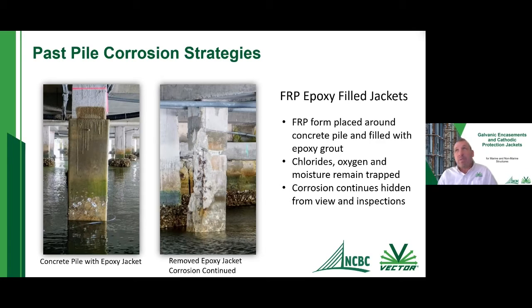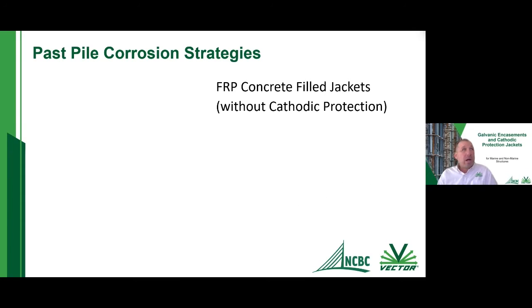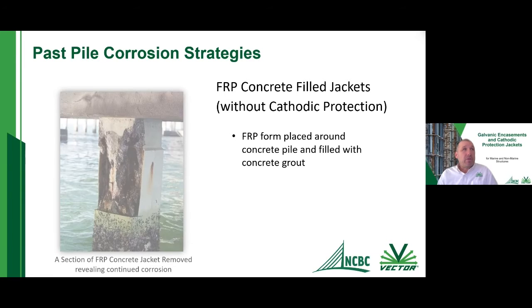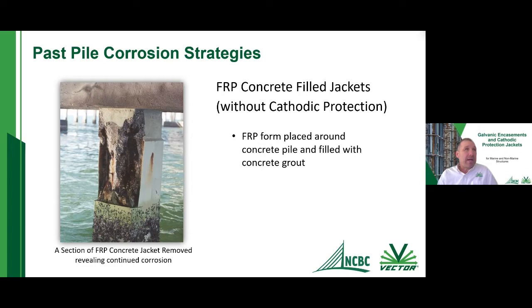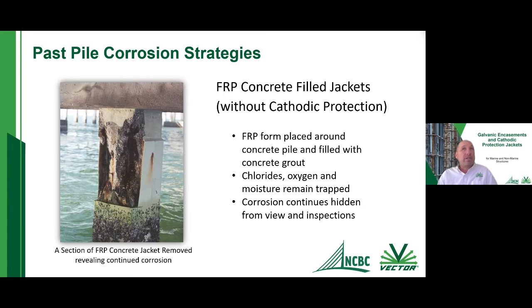And then moving on to another past strategy, which is very similar to the epoxy fill jacket: a fiberglass stay-in-place form, a concrete-filled jacket. You can see here it was a very similar thing. It's just a stay-in-place fiberglass form that's put around the pile, and then it's filled with a flowable cementitious mortar or grout. And what ends up happening behind this as well is there's still chlorides, there's still oxygen, all of this still remains behind the jacket, and corrosion can still continue.